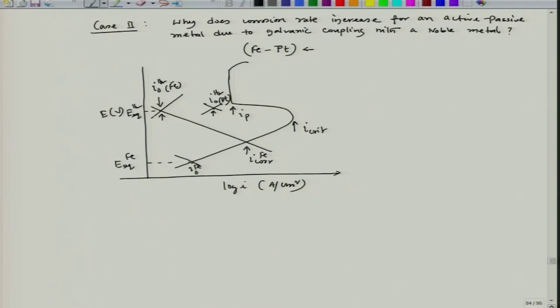So since we consider these two lines are wide apart, we can have a single line instead of double line. If this extends like this, or you can also do the theory as we have done, that particular point again would lie very close to it, as if it is lying on top of the cathodic polarization of hydrogen on platinum surface.